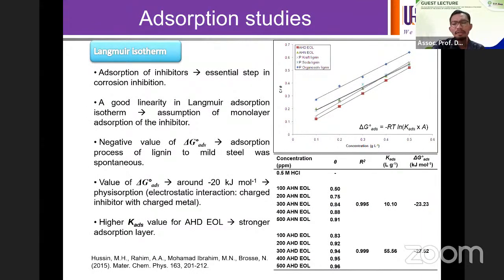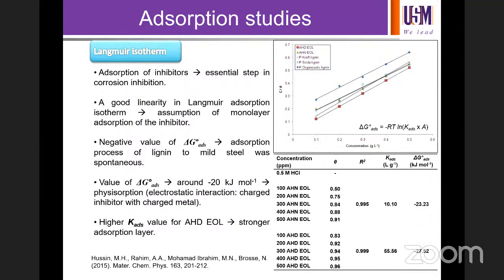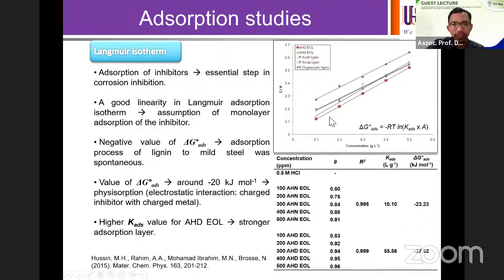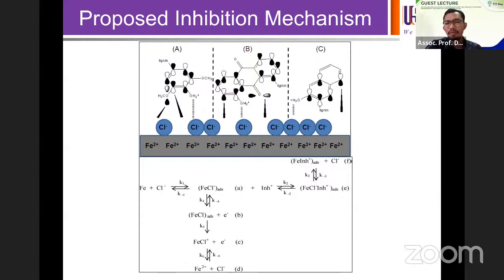So in order to justify the type of mechanism that happens during the inhibition process, we performed adsorption studies. In the adsorption studies, we fitted different isotherm models, especially Langmuir, Freundlich, Frumkin, and Temkin, and it fitted best with Langmuir. And if you calculate the Gibbs free energy, it gives us some idea that the type of adsorption is basically more of a physical adsorption. It's a type of electrostatic interaction between the charged molecules and the charged metal surface. And this is the mechanism that we proposed in our publication. And this is also supported with the modeling studies that we did.